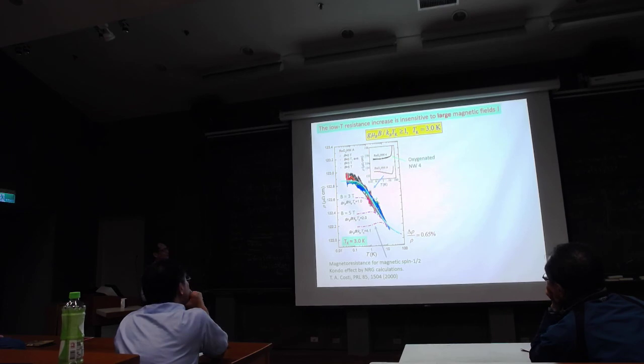However, in some of your data, it shows a weak magnetic field dependence, even though you say it does not depend on magnetic field. Yeah, here. So for example, this one. The black one is B equal to 0. However, at 3 and 5 Tesla, you see it shows a weak dependence on magnetic field, right? I don't know the theoretical details, but of course, physically, there must be a magnetic field effect. But that effect may be a few orders of magnitude smaller. Yeah, that would be a higher order effect, much smaller than this.